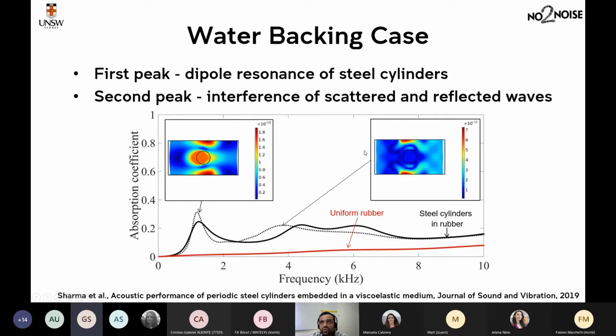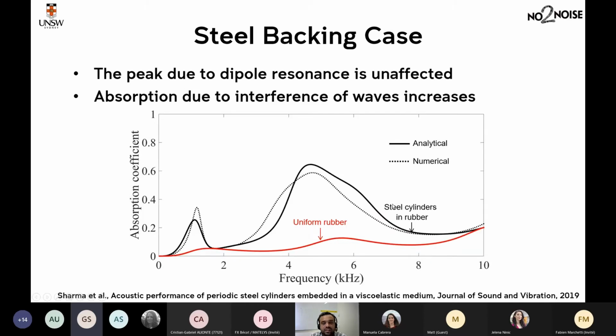But even though the impedance of water and rubber are close, they're not exactly the same, at least for the material properties I have chosen here. So there's some impedance mismatch between your PDMS medium and the fluid medium, which is water on the transmission side. So the interference between the waves scattered by your hard inclusions and those reflected by this fluid-rubber boundary creates this peak. For the water backing case, as you can see, this peak is not very significant, but when you have high impedance mismatch, you will see here in this slide. So when you have steel backing, you get a much, much higher peak at that frequency.